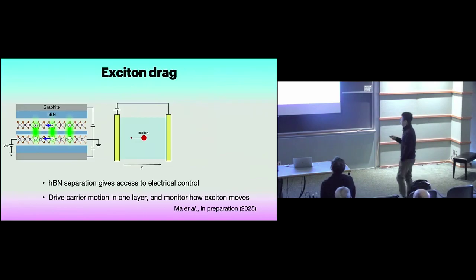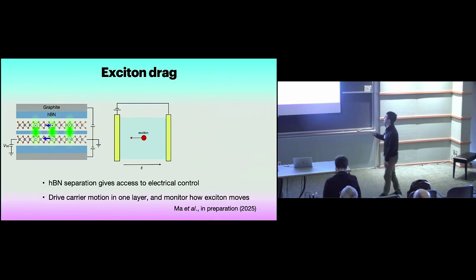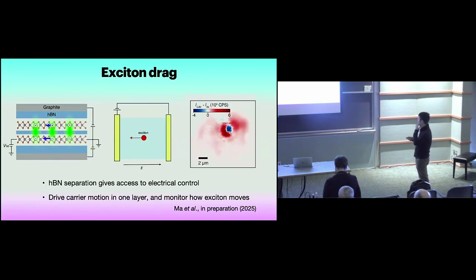Yeah. This also actually gives us electrical access, right? Because I have 2 layers separated by hBN, so you can imagine that I can create an individual contact to these layers and do transport measurements. We haven't done the full-blown transport measurement yet, but one thing we can do is to apply a current in one layer and look at how the exciton moves together. So this will be probing the correlation between electron in one layer and the hole in the other layer. So ideally, if I apply electric field, I should see the exciton moves in the opposite direction if I apply on the electron layer. So this is exactly what we see by comparing the spatial distribution of excitons under certain electric field and without electric field. We can see that they actually move in response to the electric field.